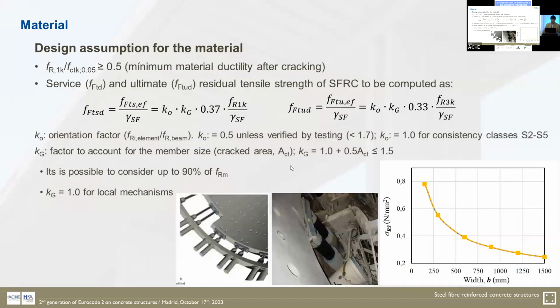In terms of design, the ratio between the characteristic value of FR1 and the characteristic tensile strength, the 5% percentile, should be greater than 0.5 to guarantee ductility of the material, especially if we are going to substitute or eliminate part of the longitudinal reinforcement. And the design value of the residual tensile strength in case of the service limit state is governed by the characteristic FR1 value.